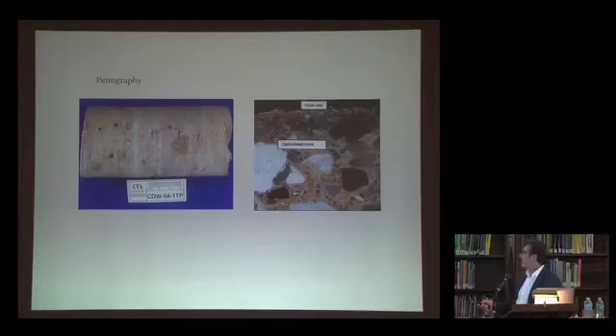So here's a core, here's the cocoon on the surface, and here is a different core in section with a stain applied to see what sections of the material had been altered. And by that, it's really pH. If concrete is not exposed to the elements, the pH will be high. As it's exposed more and more to the elements, the pH drops, and the effect on the building gets much more serious as it goes deeper and deeper in. Because once the pH drops, the rebar is in an environment where it can oxidize a lot easier and then start to cause a significant amount of problems.